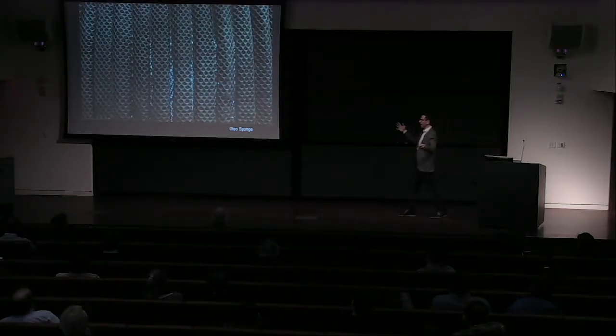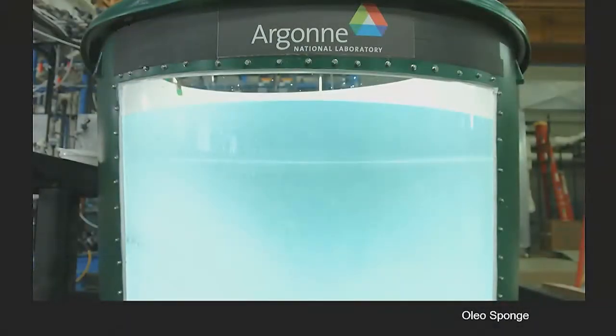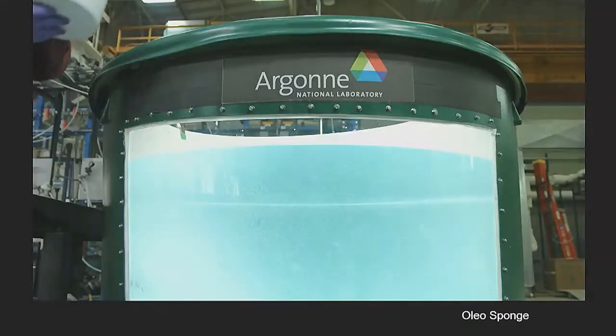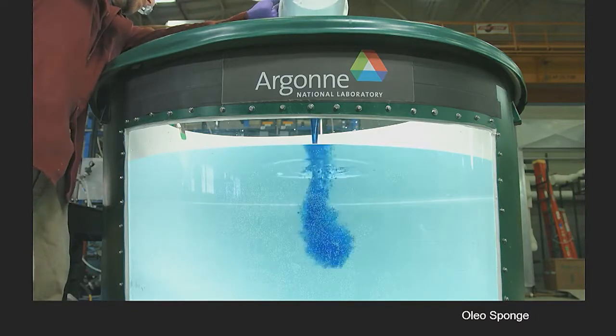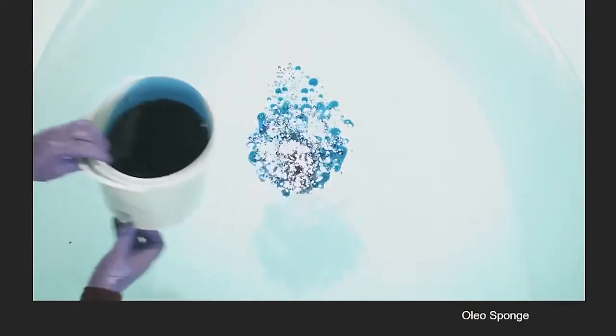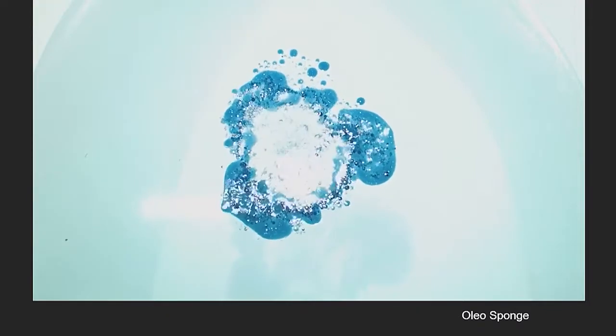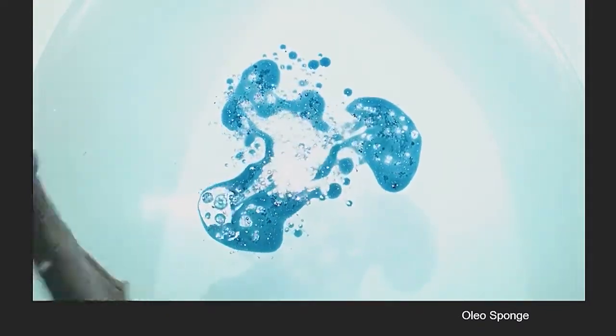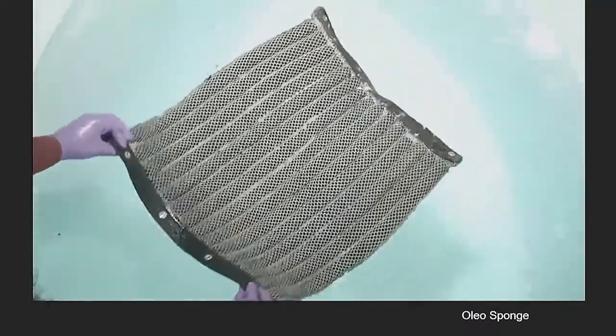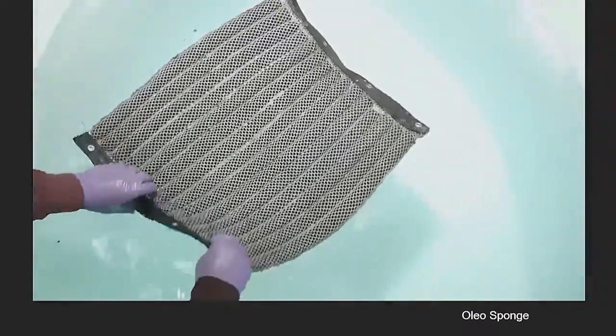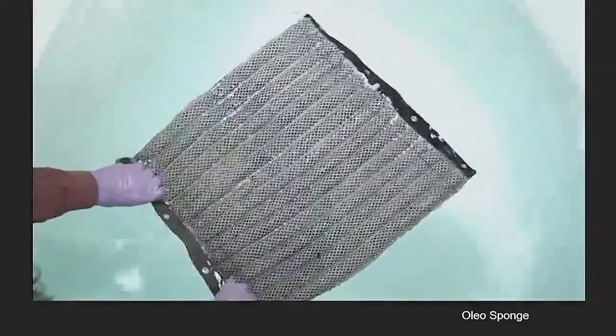So that is a pad filled with the oleo sponge, and it's in some netting to hold it together. Here's some more blue oil. Now he's pouring in, I don't know, probably half a gallon or so of oil. Interestingly enough, this is a carnival dunk tank that we're using here. That was really hard to get through procurement. But check this out. And just like the little guy, you can squeeze out that oil and reuse it over and over and over again. So we are convinced that this is an effective way to clean up surface oil slicks.